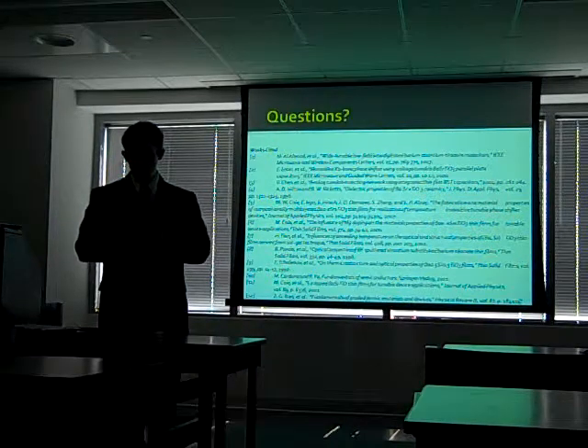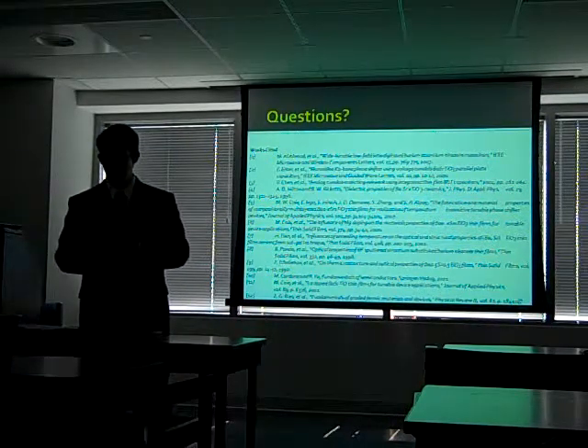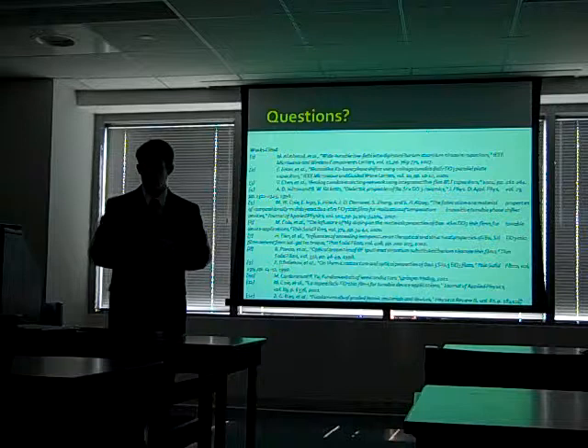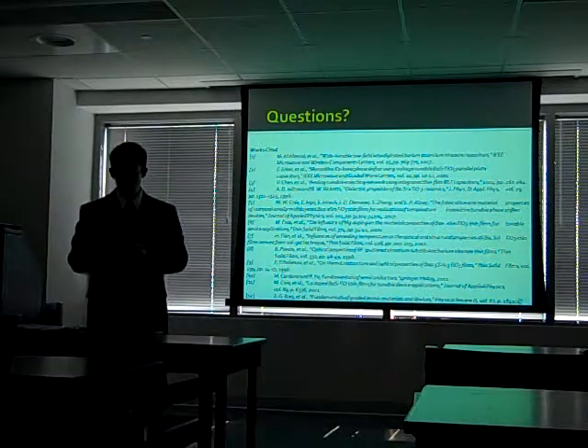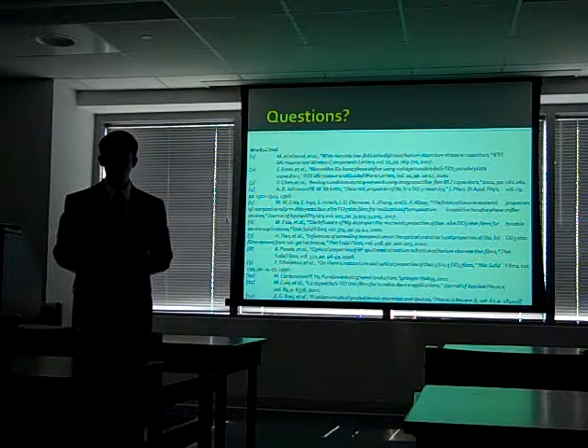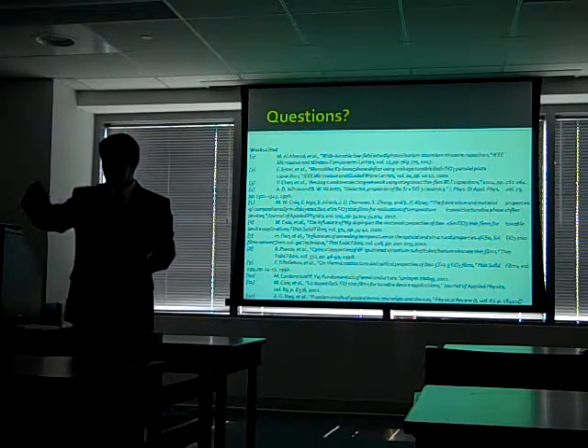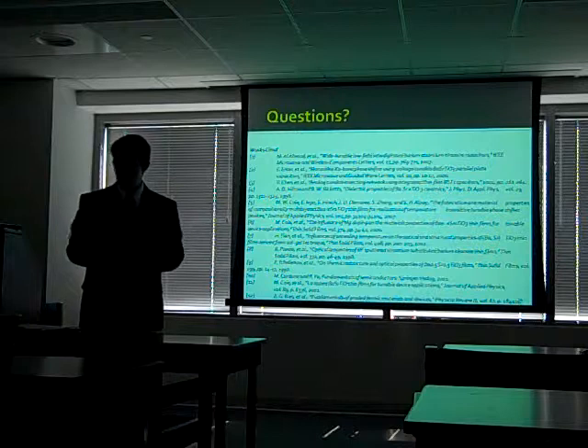You talked about the error introduced due to the several steps, but you weren't really able to test the same composition film against itself. Were you able to look at the same measurement on the same film and see what the variation was? Yes, and it works. The ellipsometer spot size is about, I use the focusing optic, so it's about 1/2 millimeter by 1/2 millimeter. Invariably, when you put a new sample on, it's going to be in a different spot, and the result is that the model still converges. You might get a slightly different thickness because, over a longer length scale, kind of with Oren's question, there are film thickness variations. And it works. Does that answer your question?